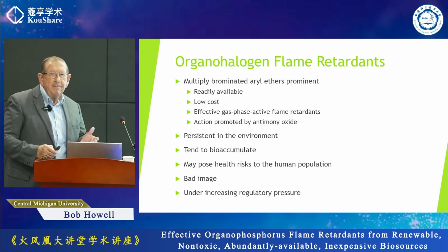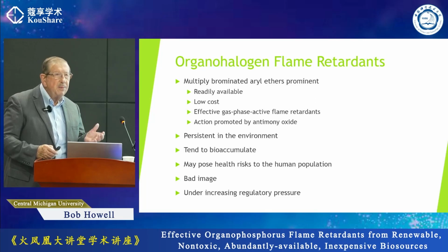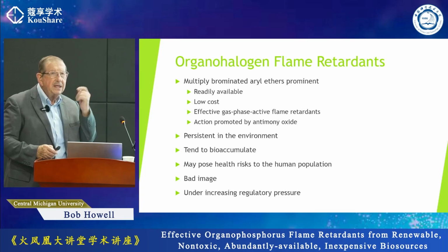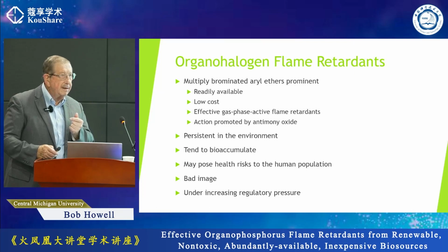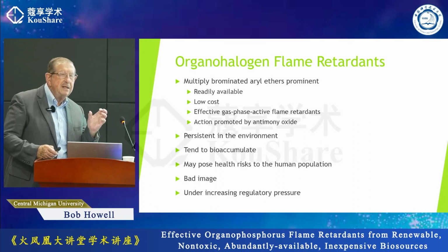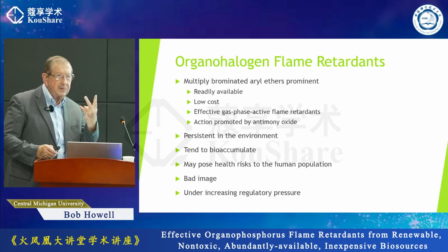In a degrading polymer matrix in which the flame retardant, the brominated material, is degrading, it's converted to antimony tribromide or oxybromides, which are volatile, get into the gas phase, and inhibit the radical reactions. And so the bromine that's present in the flame retardant is utilized more effectively. But the processes are not related. They're in parallel.